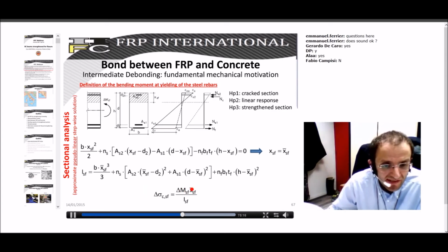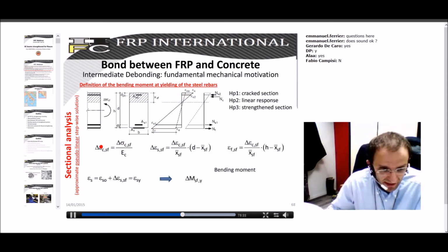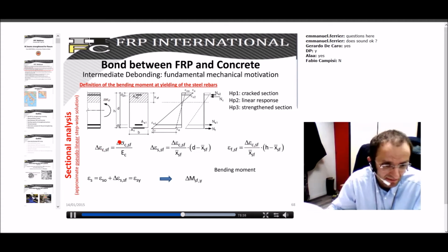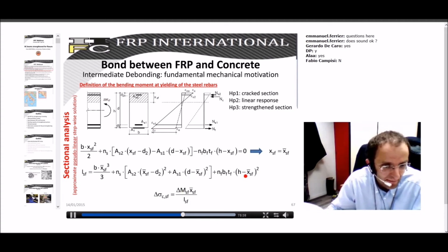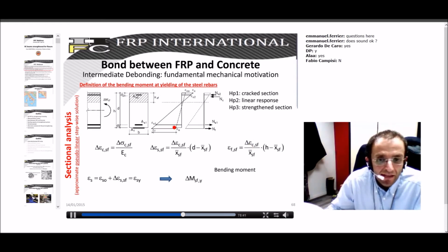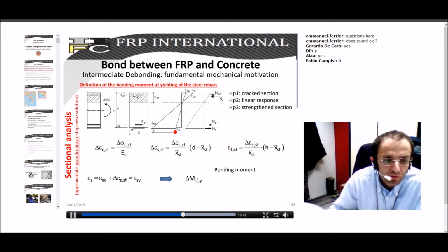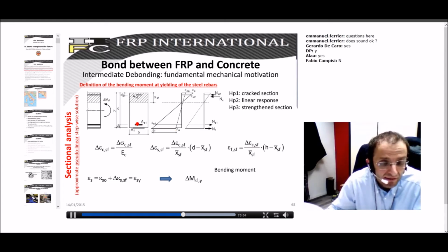And once we have evaluated the increase in sigma in the concrete and on the top chord, we can also evaluate the increase in terms of epsilon in the same chord, and also the increase at this level and also at this level. This epsilon FSF is the increase which depends on epsilon, and this means that it depends on the increase in m, at the fiber level. So this is the epsilon f. And okay, this solution works up to the yielding of the internal reinforcement.